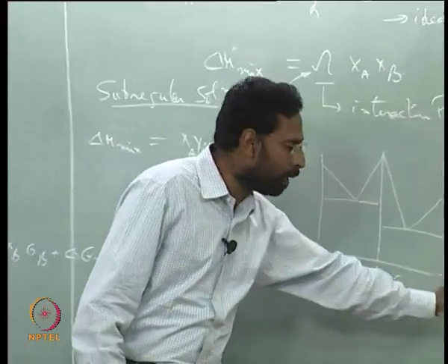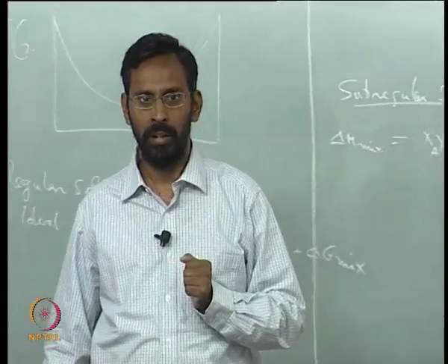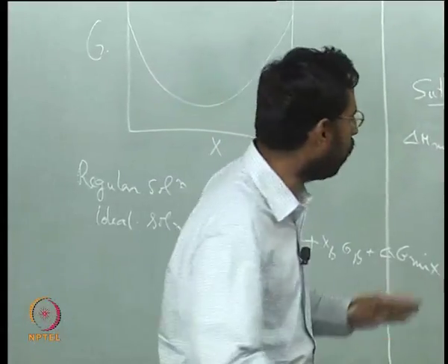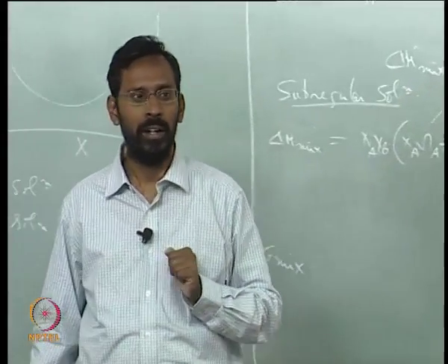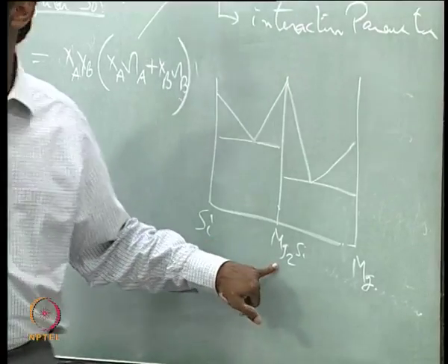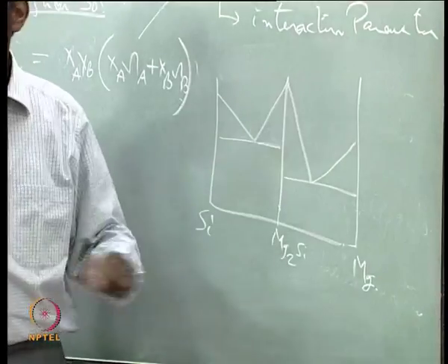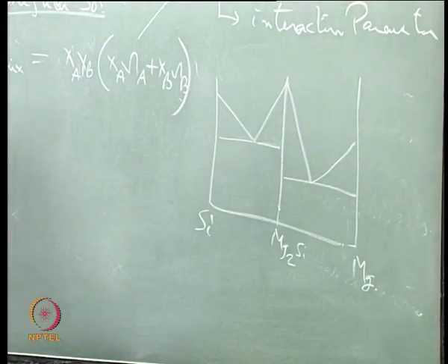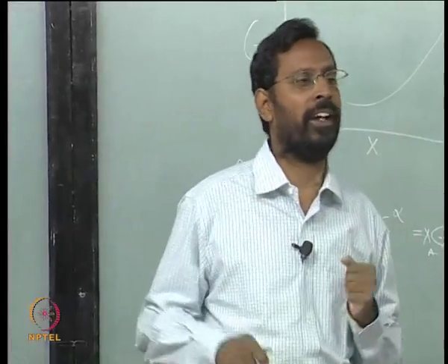And similarly on the magnesium side also, silicon does not dissolve into magnesium. There is almost negligible solubility on both sides if you carefully observe the phase diagram, but suddenly at this position there is an attraction and its melting point is higher than that of both the pure metals. This means that the interaction at certain compositions suddenly becomes attractive.